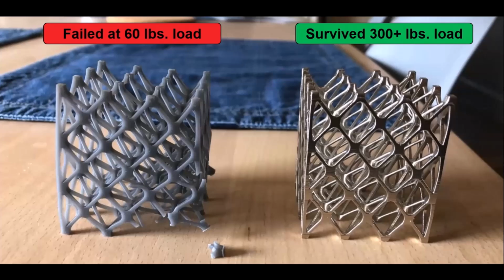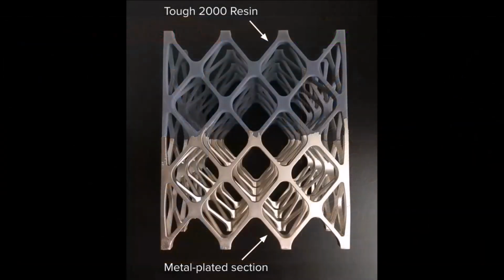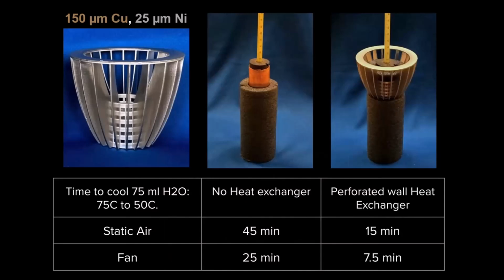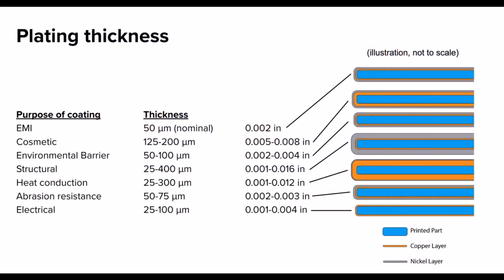As I said with Cerakote, that's the power of composites. And like Cerakote, electroplating helps increase strength, smooths and seals surfaces, and improves cosmetics. However, electroplating also adds another unique property, conductivity. Electroplating applicators can vary the ratio of copper to nickel, so by increasing the copper layer, you boost the part's electrical and thermal conductivity. Conversely, more nickel increases strength, durability, and aesthetics.